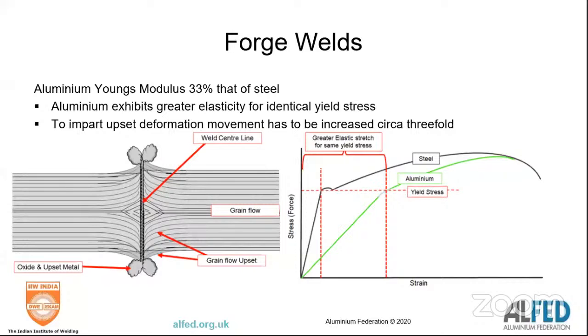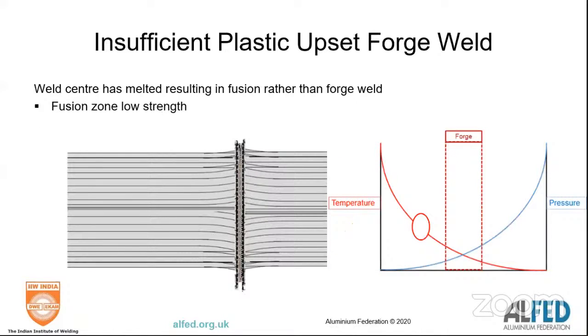That springiness is great when you're designing suspension components or crash cans or things like that, but it's a problem. So when you're forge welding it, when you're upsetting it, in essence, you've got to do 3 times more plastic deformation to achieve over steel. If you don't, particularly in a forge weld, you end up with a wide weld center line, which is effectively a fusion rather than a forge weld with poor strength. So that's the very first, easily overcome problem of aluminium, low Young's modulus.